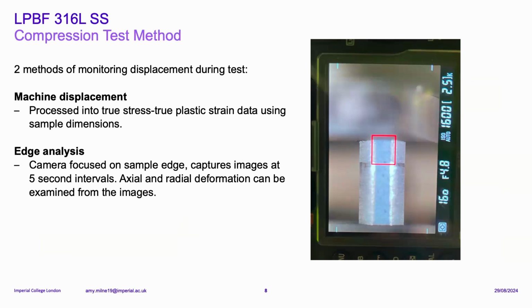So as I mentioned, I had two methods of monitoring displacement during the test. We started with machine displacement, which is directly extracted from the machine and then processed into true stress, true plastic strain data, and then edge analysis from the camera. So it was really important to focus on the edge of the sample and then put it through a MATLAB code, which detects the increase in diameter and the axial and radial deformation from the images.